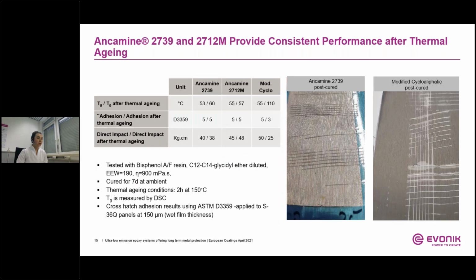Ancamine 2739 and 2712M provide consistent performance after thermal aging. To explore the durability of the cured coating after thermal aging, 2 additional sets of clear coat panels were prepared. The first set was allowed to cure for 7 days at ambient temperature, and the second set of coating cured for an additional 2 hours at 150 degrees. The glass transition temperature, the crosshatch adhesion, and direct impact resistance were measured here.